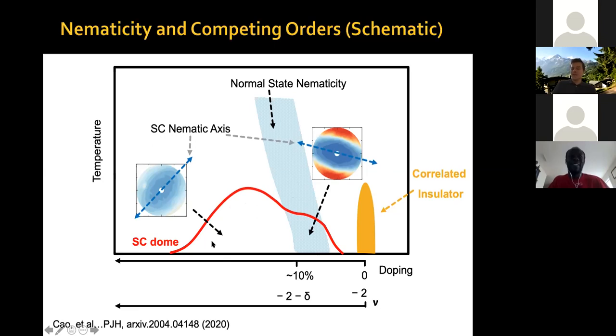Okay, so it seems that everywhere in the superconducting state, we have nematicity. What sets the direction of this ellipse in this region is not clear. Perhaps the ellipse gets pinned by a small amount of strain. Strain is not responsible for the ellipse itself, but it can locally pin it a little bit or try to pin it to a given angle. However, as we decrease the doping, as we go towards this region of doping, whatever is setting the normal state anisotropy seems to be now setting the superconducting state nematicity axis. Because there is a smooth and small angular rotation around here, but then we have a fast rotation here. So the rotation axis seems to be pinned by, or influenced strongly by, whatever is setting this normal state nematicity. So this is the picture that is emerging out of our studies.